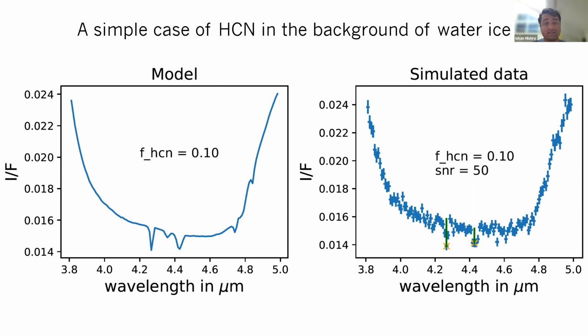I started this project by taking a simple case of hydrogen cyanide, which is a good test species because it has sharp features, as you can see in this region. Also, cyanide features have been detected on the other Galilean moons, so we just wanted to see what its detectability looks like. I took it in a simple background of water ice, and then simulated observations as a function of different SNRs and abundances of hydrogen cyanide. You can see that in the simulated data, you can still clearly see those features.